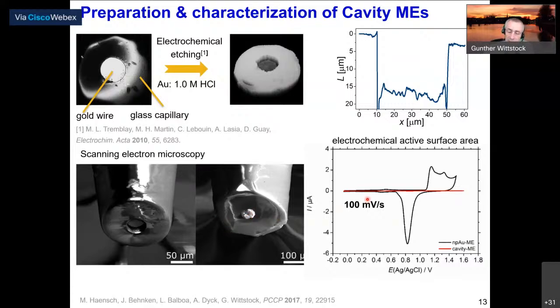Once this cavity is filled, we can record cyclic voltammograms, and you see here the response of those. The red curve shows the cyclic voltammogram of the recessed gold electrode, which is just the empty cavity microelectrode. And then the black curve shows you the response of that electrode when the cavity is filled with nanoporous gold. Since this is nanoporous, it has a tremendous surface area, and we get a nice surface voltammogram of the gold. In comparison to that, the response of the gold electrode, which forms the recessed microelectrode, is negligible. So all the response comes from the porous material.